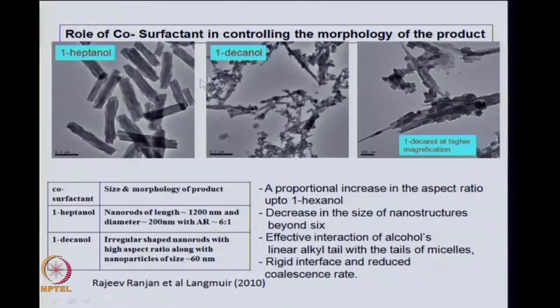So, this is already what we discussed in heptanol and decanol. We can see that the morphology changes, and up till 6 carbons in the co-surfactant the size of the particles increases.